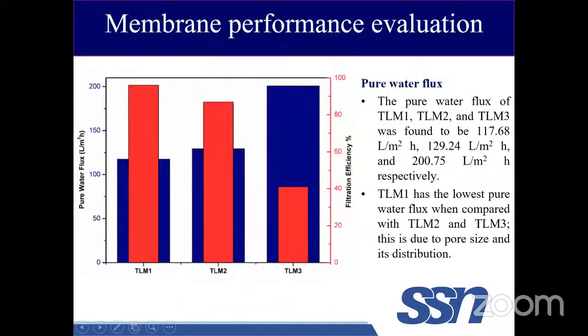Then we checked the pure water flux and filtration efficiency. As you can clearly see, the pure water flux was quite less for TLM1 because of its lesser amount of pore former agent, but the filtration efficiency is higher, right? Which is not the case in the other two. In TLM3, we have a higher pore former agent, so the pure water flux is higher, the water passing through the membrane is higher, and the filtration efficiency is lesser.